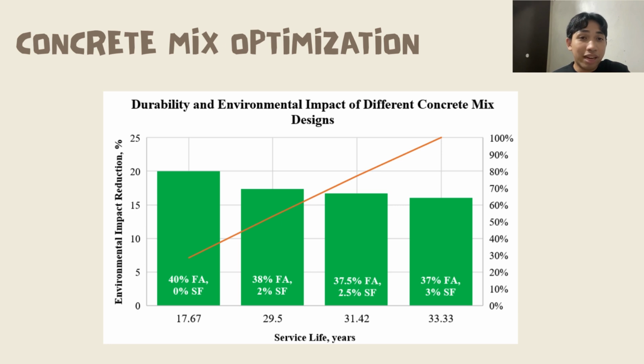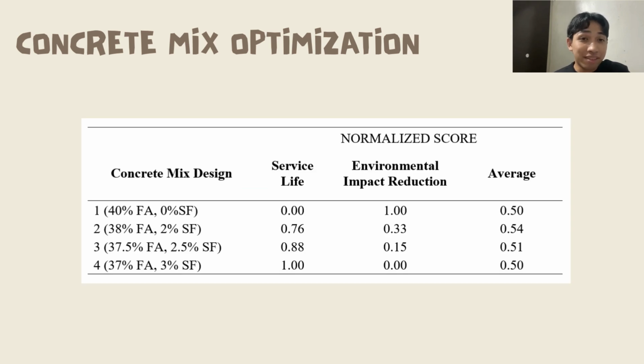The team identified 4 different mixes, and the plot shows the mixes' durability and environmental impacts. All that's left is to determine which mix is the most balanced. We did that by normalizing the values, and upon doing so, we determined mix 2 with 38% fly ash and 2% silica fume as the most optimal design.